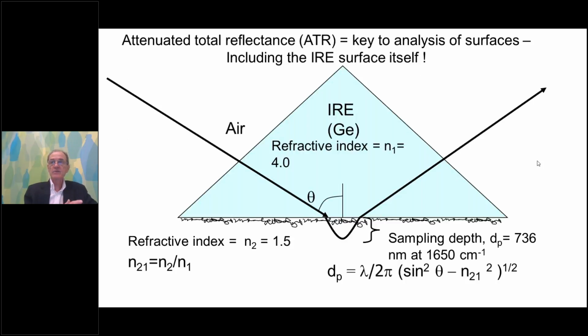One way to do that is to use FTIR with so-called ATR, or attenuated total reflectance optics. So what we do in ATR is we send our IR light through an IRE. It hits an interface and it's totally internally reflected, but it establishes a standing wave right at the interface. And now that radiation can interact with whatever is on the surface of the IRE out into space to some sampling depth d sub p that's about a micron or so. And so we can obtain spectra looking from the surface of the IRE out into solution using ATR.